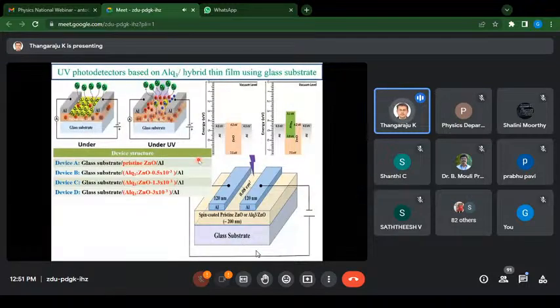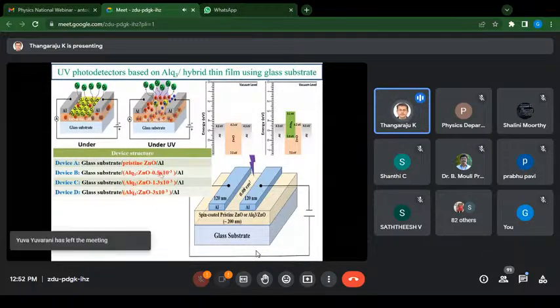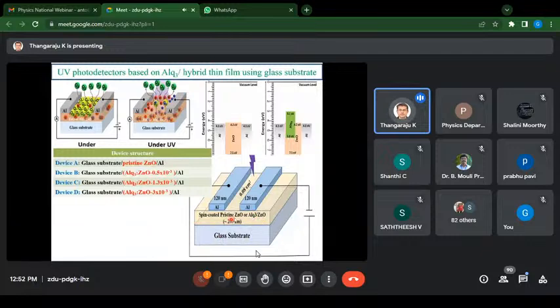So this is the typical device. We have typical UV photo detectors we have fabricated in our lab. You can see that the AlQ3 is incorporated at different concentrations, and then we have made the devices. This is the typical device structure. So onto the glass substrate, the hybrid thin film or the pristine for the reference is deposited by the spin coating process, over which the electrode is coated by the thermal evaporation process.